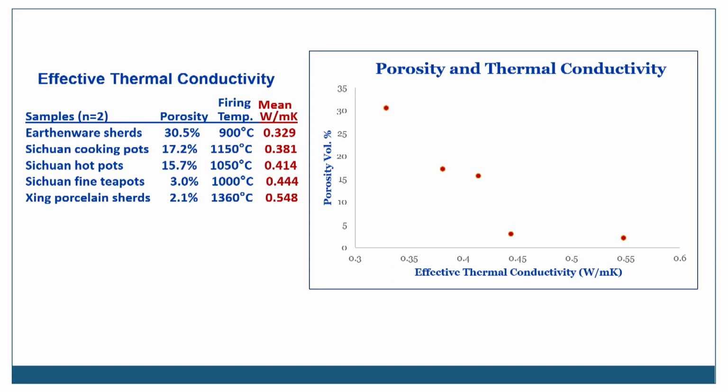Here we see some comparative results for some archaeological and ethnographic ceramics. Traditional thermal conductivity measures are done using laboratory prepared specimens, not on real sherds, mainly because sample constraints generally preclude the use of real sherds. Fairly large, thin, and very flat discs are required. So 3D image analysis is a great addition to the toolkit because it's easy to include any number of real sherds, just keeping in mind that porosity values might change somewhat during use and burial.